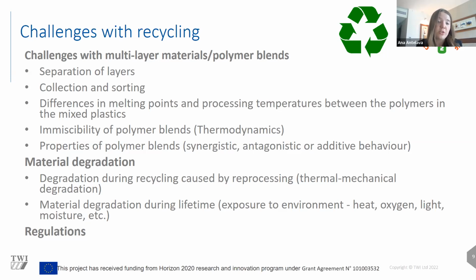Another very widespread challenge with recycling is material degradation. And usually there are two types of degradation that take place. There's the degradation during the recycling process itself. So there might be some thermomechanical degradation that decreases the quality of the final product. And another is material degradation during the product's lifetime. During the lifetime, the product might be exposed to various environments such as heat, oxygen, light or moisture, and all of this affects material quality. And of course, after recycling, this might have an effect on the quality of your final product.